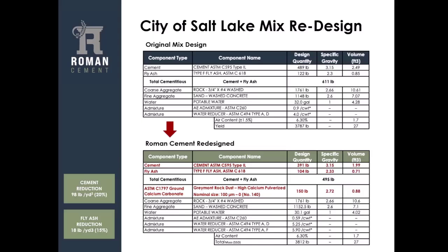This is the city prescribed mix design: 489 pounds of cement per cubic yard, 122 pounds of fly ash per cubic yard. We reduced the cement by 20%, nearly 100 pounds per cubic yard, and reduced the fly ash by 15%. So the total cementitious went from 611 pounds per cubic yard to 495 pounds per cubic yard. And then we replaced that with 150 pounds of pulverized limestone, which was still quite a bit less expensive than both the cement and the fly ash, so ultimately the cost went way down, even though we had to use a little bit more admixture to get the right flow. We had a target air content of 6.3%, and the slump had to be about 5 inches.